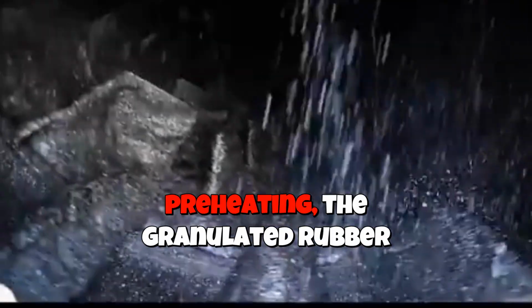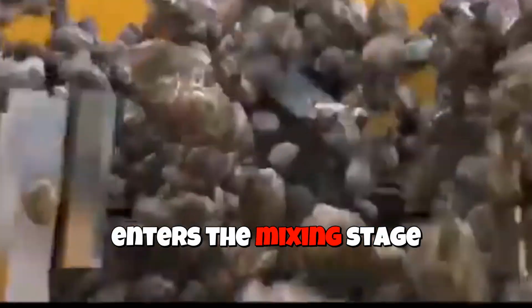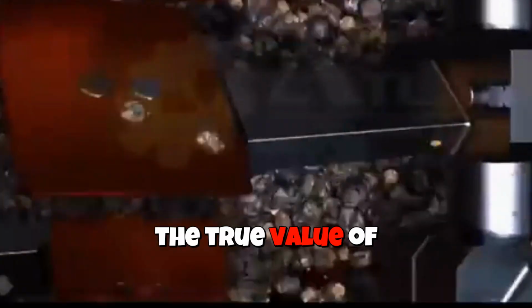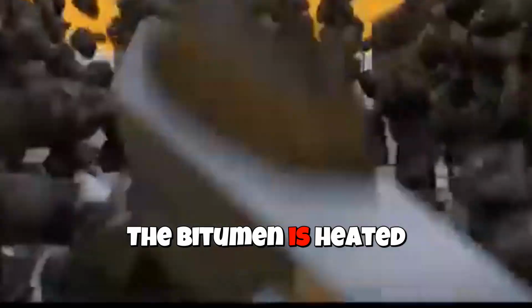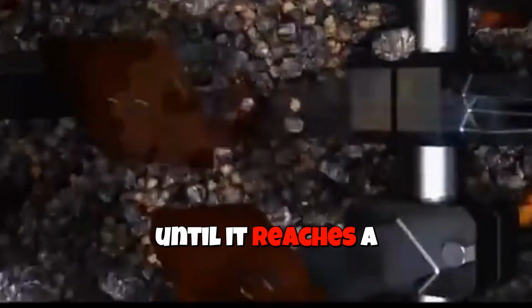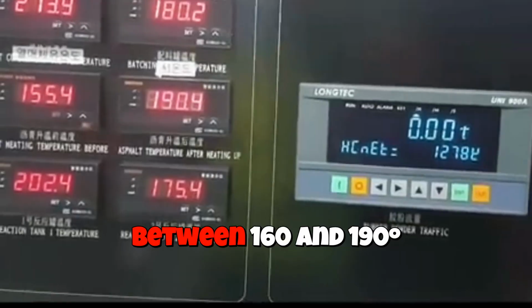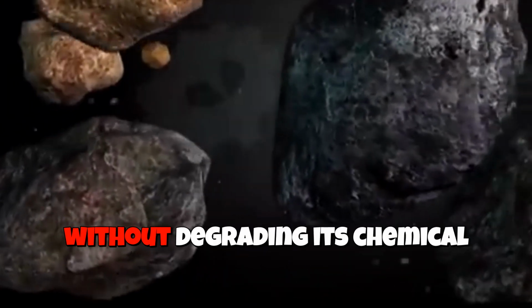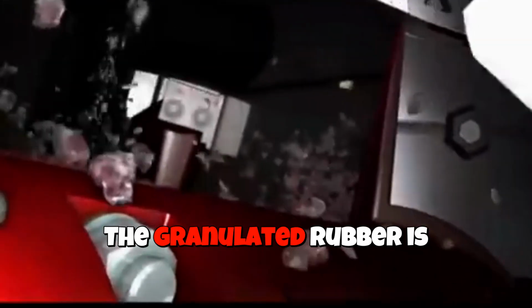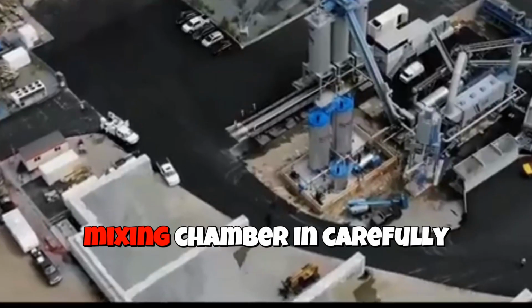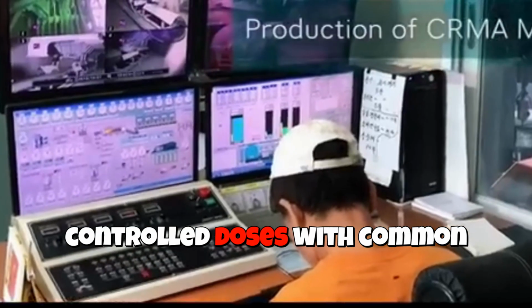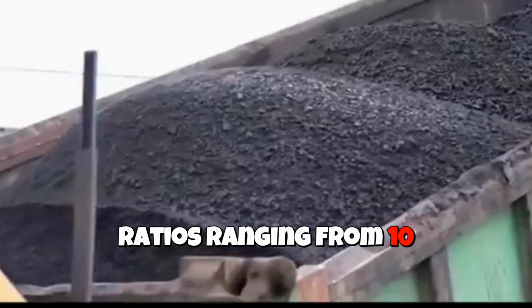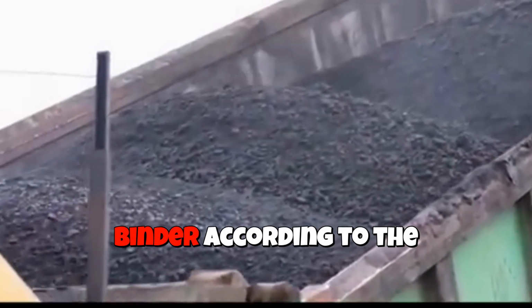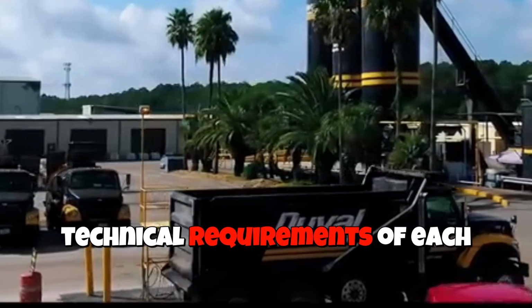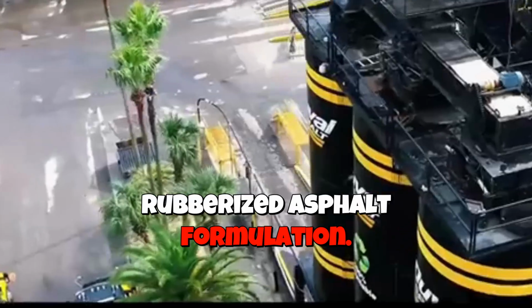Immediately after drying and preheating, the granulated rubber enters the mixing stage with the bitumen, where the true value of recycling is created. The bitumen is heated separately in storage tanks until it reaches a stable liquid state, usually between 160 and 190 °C, ensuring appropriate flow without degrading its chemical structure. The granulated rubber is then introduced into the mixing chamber in carefully controlled doses, with common ratios ranging from 10 to 20% of the total mass of the binder, according to the technical requirements of each rubberized asphalt formulation.